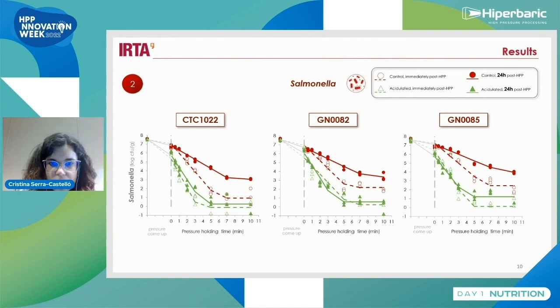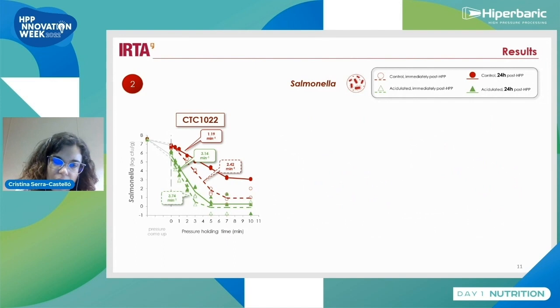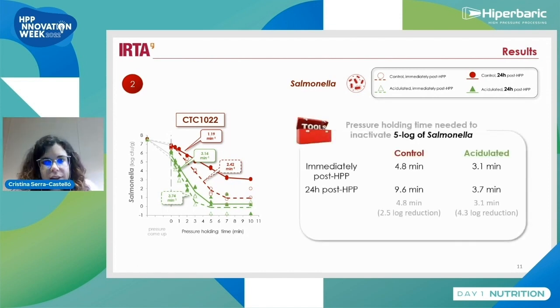As we observe that all the strains have the same behavior regarding the impact of these 24 hours post high pressure processing, we can now focus only on CTC 1022. We observed that enumerating the counts of Salmonella 24 hours post high pressure processing also results in a lower inactivation rate compared to that obtained when enumeration was carried out immediately post high pressure processing. And these kinetic parameters can be used as a tool. And a tool for what? A tool to estimate the pressure holding time needed to inactivate 5-log of Salmonella.